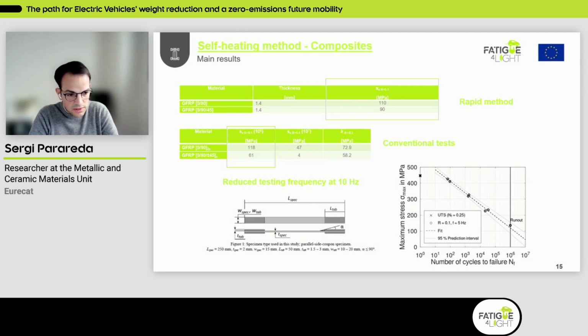And here also we want to highlight that these methods are even more important in this case, because the testing frequency has to be reduced to avoid the effect of the strain rate on the fatigue behavior of these materials. And just to show that by using this rapid method, we can obtain the fatigue resistance, or a first approach of the fatigue resistance, for composite material.